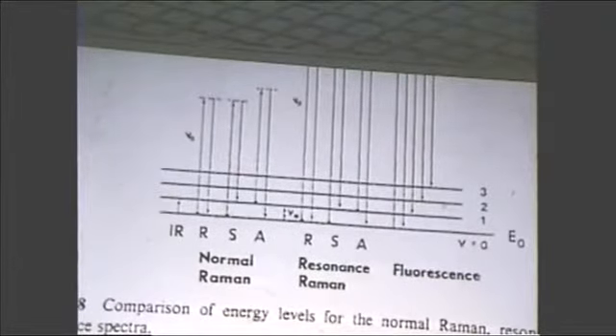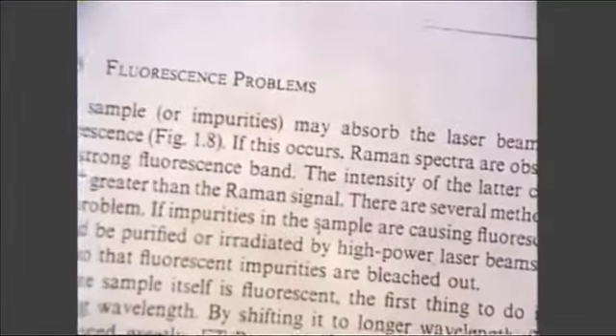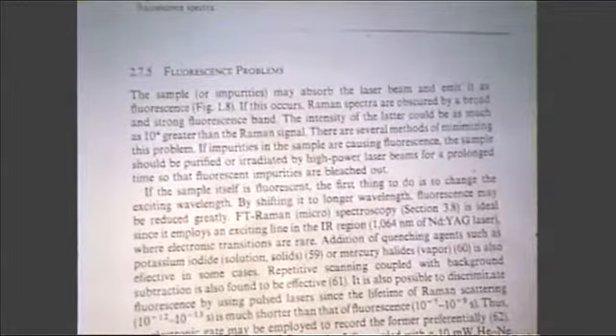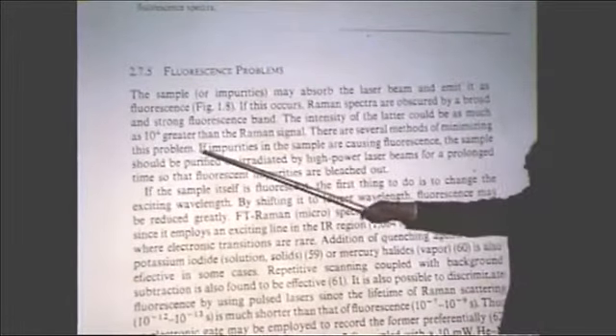catalyst. And there have been some in situ studies done, in particular by Knözinger and by Lunsford, looking at oxidation catalysts. This fluorescence is very strong. This is just an excerpt from a book by Stencil that he wrote about Raman spectroscopy applied to catalysis. And he says here that the intensity of the latter, namely the fluorescence, can be as much as 10 to the 4th times greater than the Raman signal, so you have a very difficult time pulling this tiny signal out of this fluorescence.